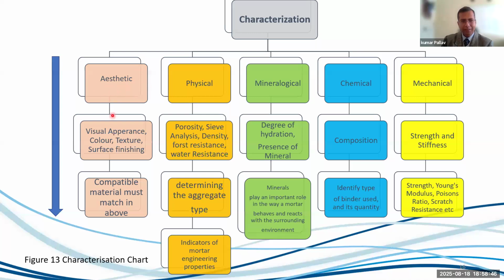If we talk about aesthetics, it definitely shows you visual appearance, which covers color, texture, and surface finish, right? Going further down, it shows compatibility: the material must match or closely match your original mortar. Further, under physical properties, you have porosity, sieve analysis, density, frost resistance, and water resistance, right? And you need to determine the aggregate type. If your mixture or whatever aggregates you are using, that will decide the mechanical properties, as they are very much linked, so your indicator must be very close to that.